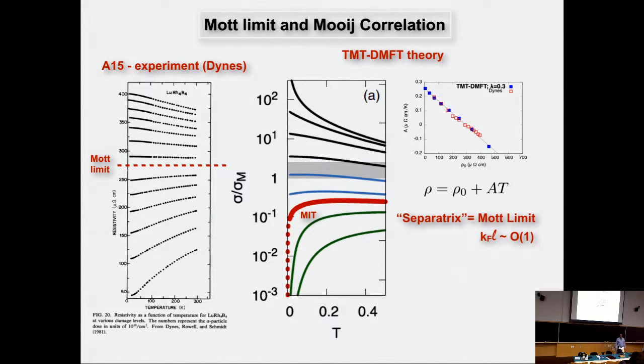Now, whether this is actually true exactly or not in a better approximation, I'm not 100% sure, but what I know, for example, from 2 plus epsilon within Finkelstein theory, is that the density of states actually goes to zero pretty robustly in the insulator. So I believe that this is in fact true, that the insulator always has a vanishing density of states in a disordered limit. Right. So in that sense, wouldn't one like to define a true metal insulator transition as the point when you start to see the exponential behavior?